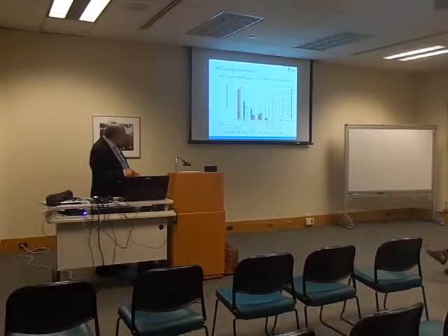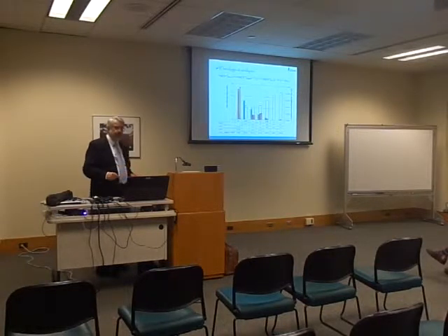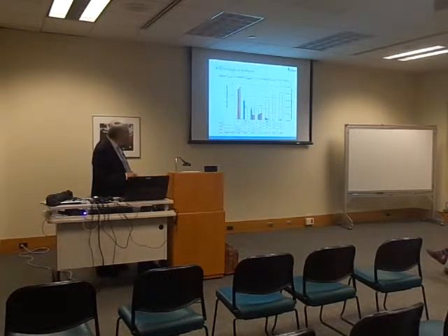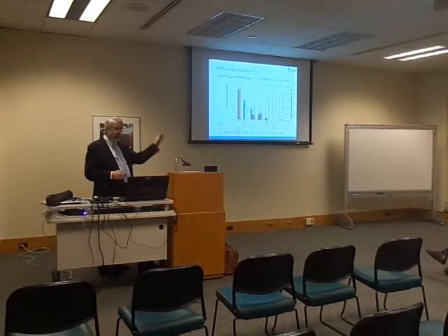Also, it was interesting that very soft rejuvenators, the red lines here show the stiffness of the rejuvenator, interacted best with the bitumen and, we'll see it later, resulted in the highest reduction. Stiff ones did not. Look how stiff this was, and look how little its interaction was. And when we look at the stiffness plots, you recognize that this was not a good choice.